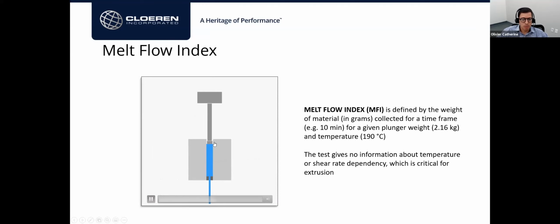But so you are melting a polymer and pushing it with a standard weight, collecting the material coming out for a time of 10 minutes and measuring that weight. And so you have a pretty meaningless unit of grams of polymer per 10 minutes with this size of weight that you used at a given temperature. So it's very hard to translate that number into something meaningful to design or troubleshoot any process.